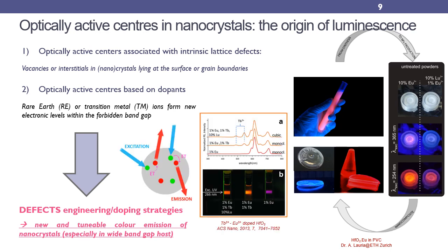Moreover, other doping strategies permit the doping with two ions. For instance, hafnium oxide can contain terbium and europium, and the energy transfer from one ion to the other occurs, giving rise to a composite luminescence spectrum and a change of the final emission colors according to the concentration of the two dopants.